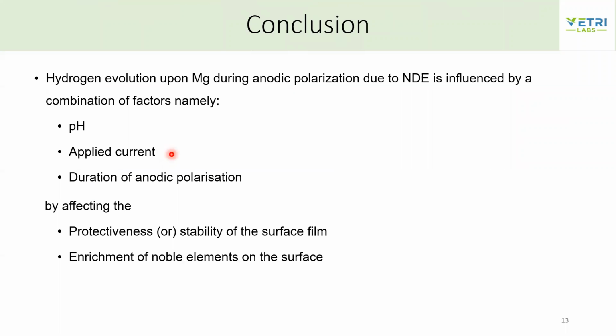The conclusion of their paper is that the hydrogen evolution upon magnesium during anodic polarization is influenced by a combination of factors—not just pH, not just applied current, not just the duration of anodic polarization, but a combination of all. It could be pH plus applied current. It's not always just the applied current.